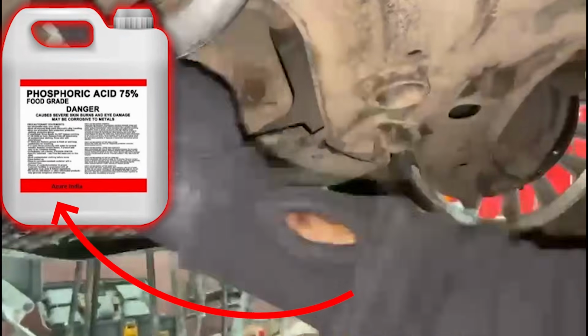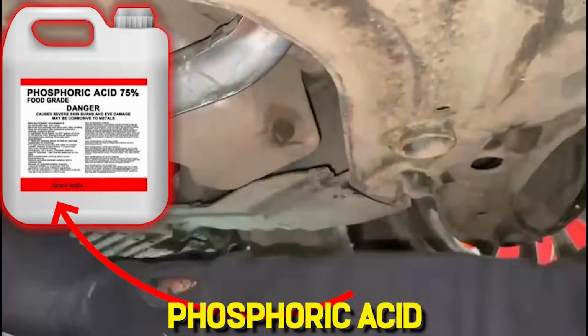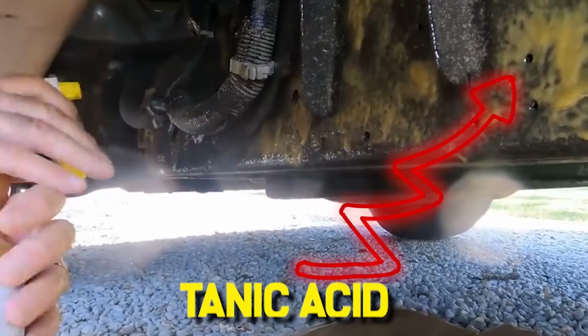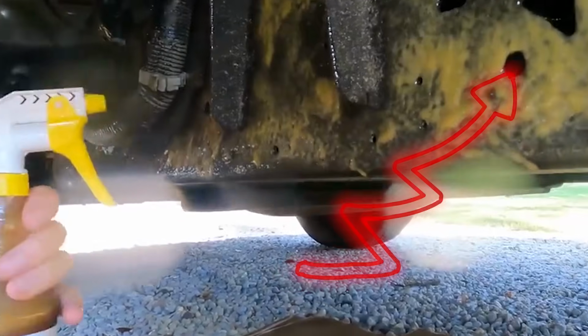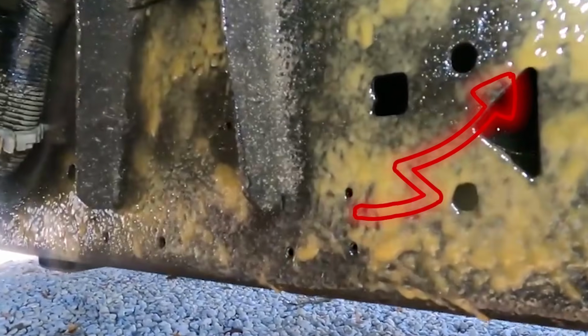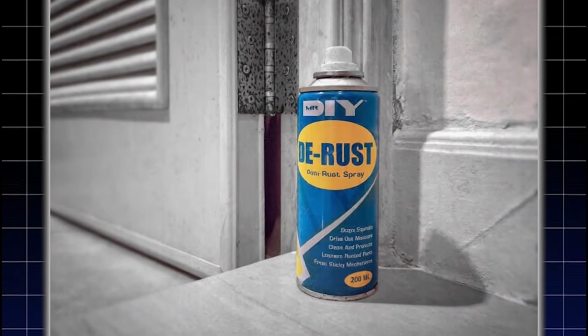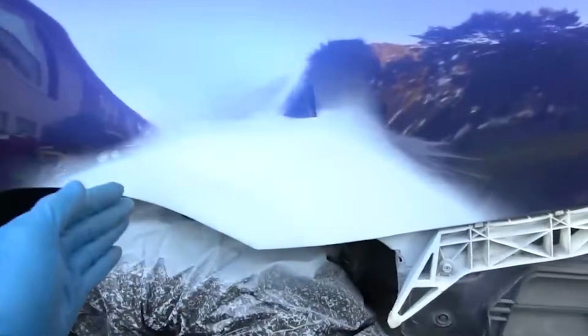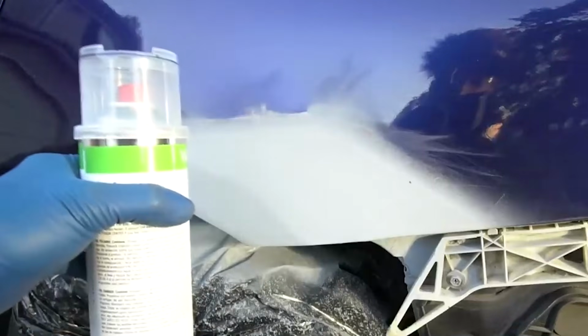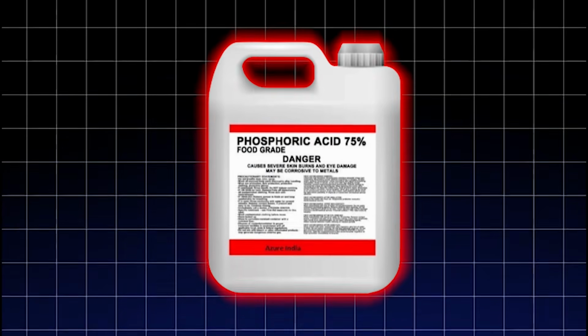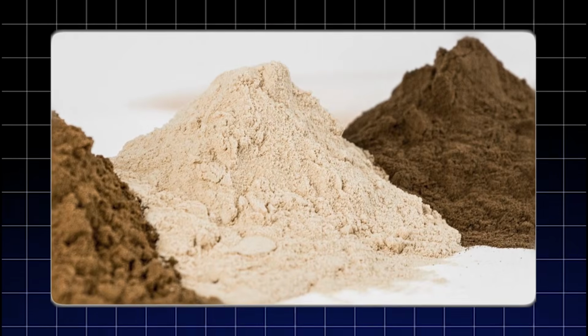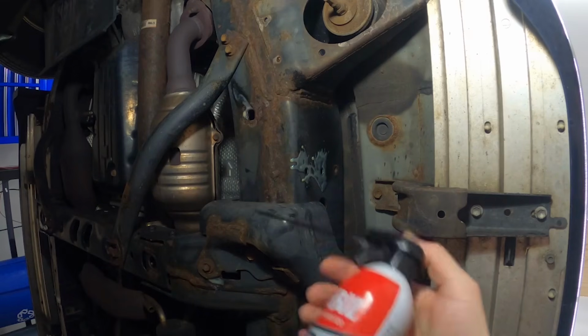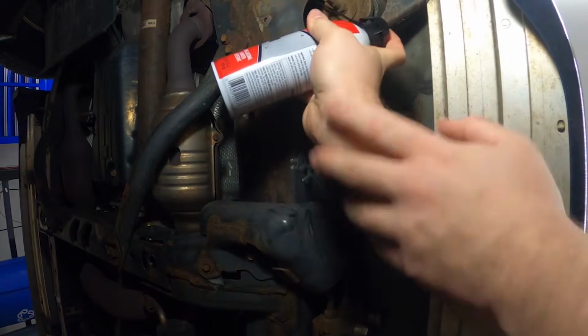Generic rust converter sprays use phosphoric acid at low concentrations combined with a tannic acid secondary chemistry. The difference between a product that uses tannic acid effectively and a generic spray that uses it ineffectively is concentration and contact time chemistry. Generic sprays are formulated for ease of application and fast dry time. Fast dry time is incompatible with adequate contact time for either phosphoric acid or tannic acid chemistry to complete their conversion reactions on anything beyond the lightest surface rust.